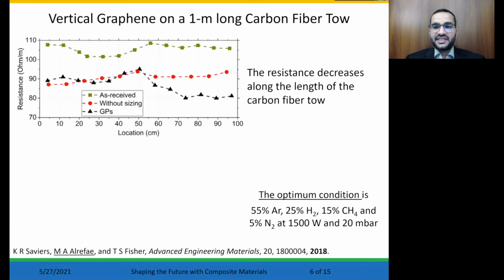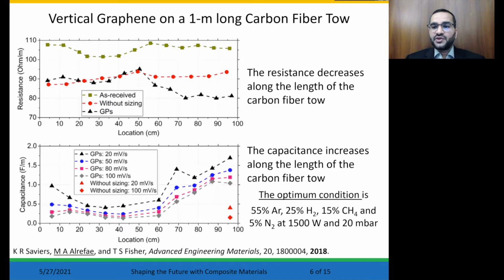We selected the optimal condition from the optimization process and demonstrated vertical graphene deposition in a roll-to-roll fashion for a 1 meter long carbon fiber tow. We measured the electrical resistance and capacitance for several segments through the 1 meter sample. The electrical resistance starts to decline in the second half of the sample, indicating a higher deposition of vertical graphene. Similarly, the capacitance starts to increase in the second half of the sample, in agreement with the electrical resistance measurements.